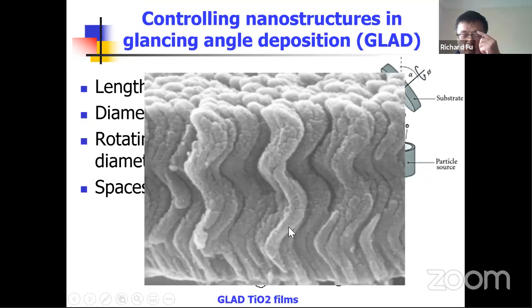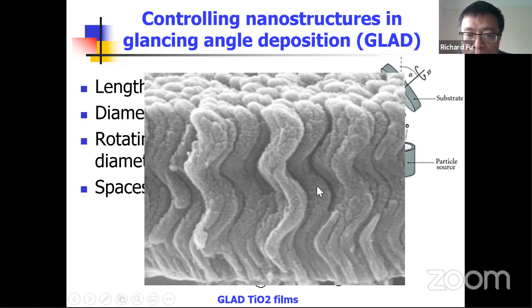So we actually grow zinc oxide film and titanium oxide film using this method. These are spiral patterns of the titanium oxide. These are very good for optical applications and also for gas sensors and catalysts.